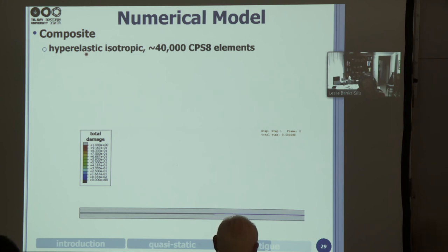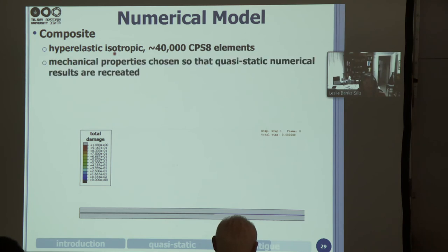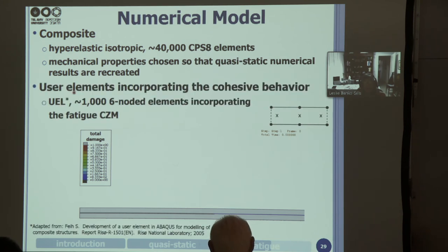And we tell you that we used a hyperelastic isotropic model because there was so much numerical error in carrying out the fatigue in the linear elastic model. But what we did was we chose mechanical properties for the hyperelastic isotropic model so that we reproduced the quasi-static numerical results. And again, we used 40,000 eight-noded plane stress elements. And we have our user elements, which are six-noded with three integration points ahead of the crack tip.